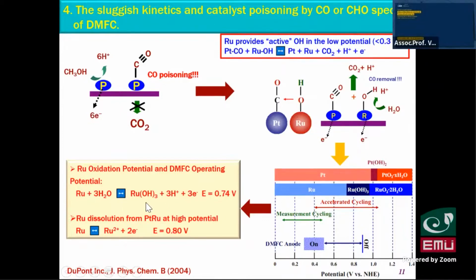However, when people use ruthenium, ruthenium also has an oxidation potential within the fuel cell operating potential range, as shown in this reaction. At a potential of 0.74 volts, ruthenium becomes ruthenium hydroxide, leading to ruthenium dissolution from the platinum-ruthenium alloy at high potential.